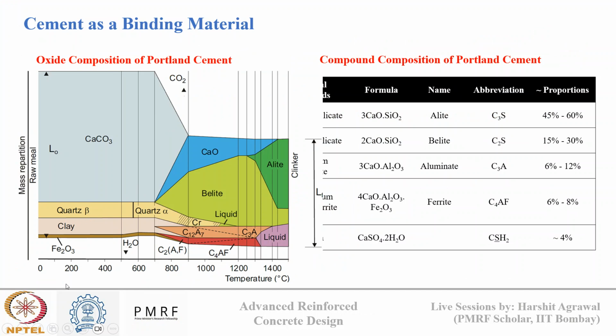So initially, in this raw meal versus temperature diagram, we have limestone, clay and quartz and iron oxides which are present up till 600 degrees Celsius. They lose moisture, and the clay part and quartz part may also give some phase conversion from beta quartz to alpha quartz. Then beyond 600 degrees Celsius, calcium carbonate starts to decompose into CaO and liberate CO2. Then belite formation and calcium aluminate formation start. And then beyond 1200 degrees Celsius, we see belite starting to convert into alite, while calcium aluminates start to appear in the form of solid solution.